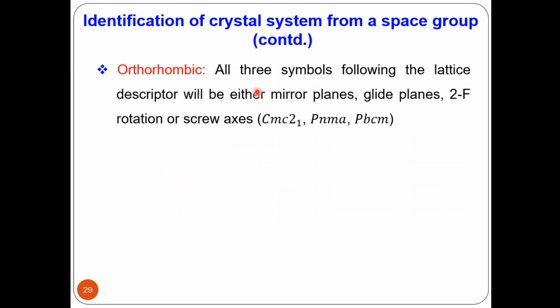For the orthorhombic crystal structure, the identification is that all three symbols following the lattice descriptor will be either mirror planes, glide planes, 2-fold rotation, or screw axes. Like in this case, this is the lattice descriptor, and we have a mirror plane, a glide plane, and a screw axis. A glide plane, a mirror plane, and a screw axis. A glide plane and a mirror plane. If this is the case, then yes, that would be an orthorhombic crystal structure.